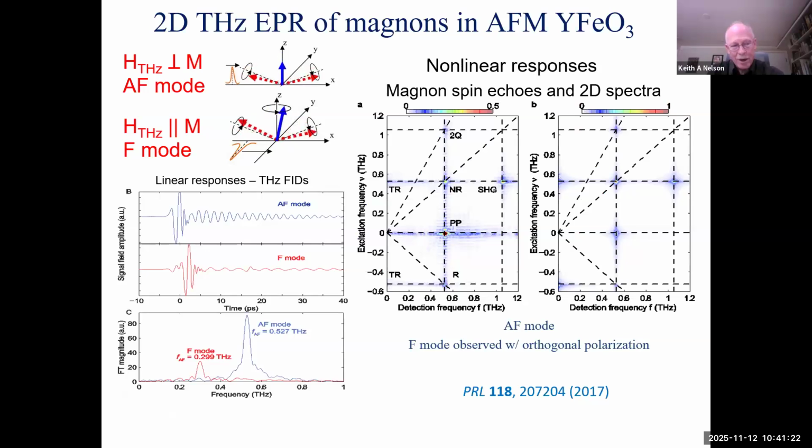But where we've really focused our efforts aren't on molecular systems, but collective spin waves or magnon modes. And what we've studied are crystalline systems that are nominally antiferromagnetic. That is, they have two magnetic sublattices that are opposed to each other, but there's an interaction between them that leads to a canting of the sublattices. So there's a small net magnetic moment. And then there are modes of collective spin modes that deviate from that equilibrium, either through precession of that moment or by variation of its amplitude.